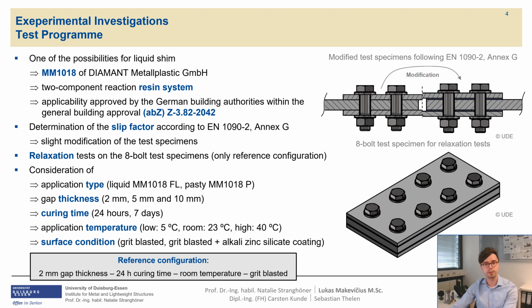In terms of the slip factor test, several variables such as the application type, here liquid or pasty type of the material MM1018, gap thicknesses of 2 mm, 5 mm and 10 mm, as well as curing time and application temperature have been defined and will be investigated over the course of the project. Also, two different surface conditions were considered: grit-blasted surface condition and grit-blasted surfaces with alkali zinc silicate coating. The reference specimen configuration for the slip factor test as well as the relaxation test has been set to 2 mm gap thickness, 24-hour curing time at room temperature and grit-blasted surface condition.